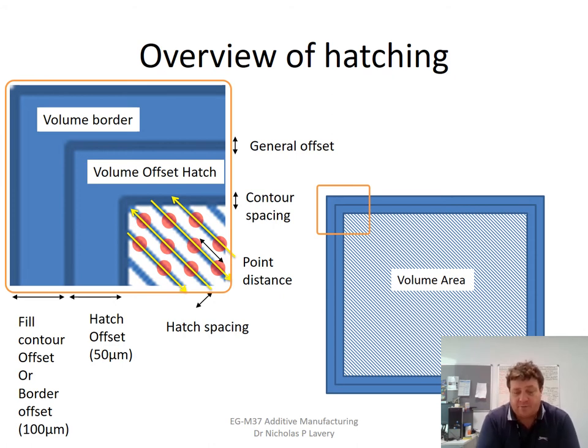So what we're going to focus on now is going back to the Renishaw machine, which you've already had an introduction to in Lecture 4, and which you'll probably have a chance to see in the Renishaw-based systems, with the new AM400 or AM500, in the labs. They're pretty similar, but we're going to concentrate on the process control parameters, which are mainly varied in these machines. So at the level of each scan, we'll have a volume area, which is the internal part. In this case, we're looking around the side of a cube which is being built up, but there's no reason why this couldn't be some random contour at any Z level.